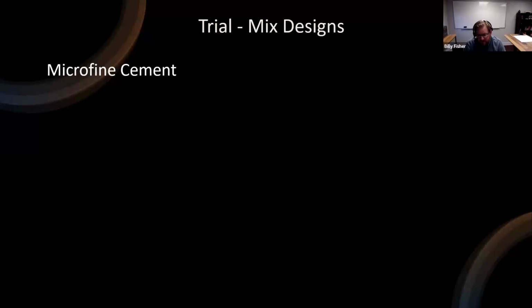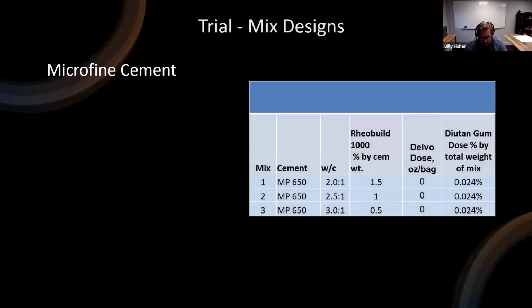We opted for a microfine cement. We ran a few different mixes in the lab just to determine what would be the best option for us. We ran a 2-to-1 water cement ratio, a 2.5-to-1, and a 3-to-1. We were looking at how much the mix was going to bleed, what the bleed percentage was, and what the strength was.